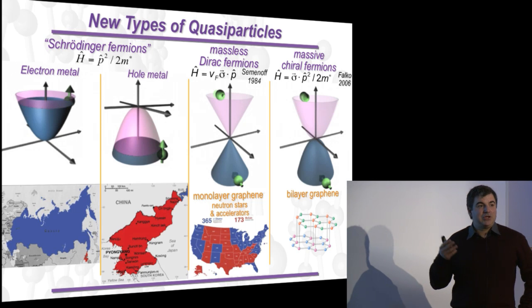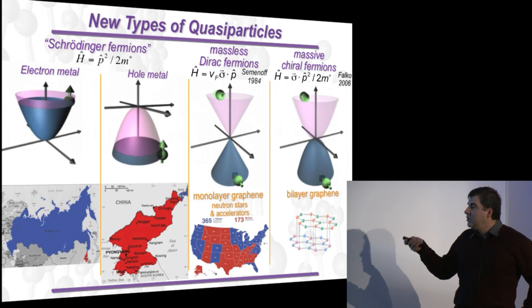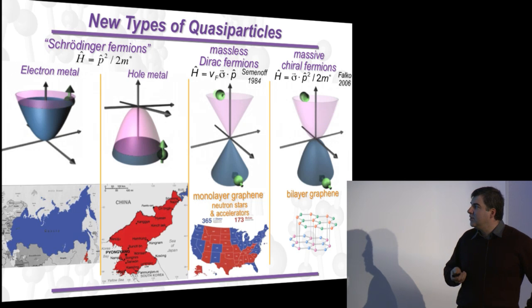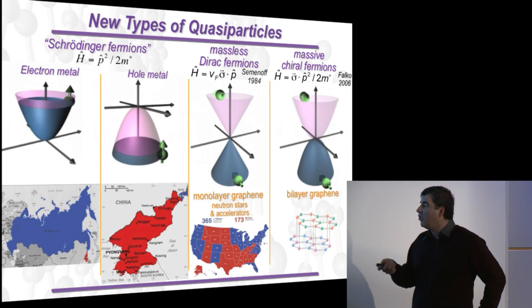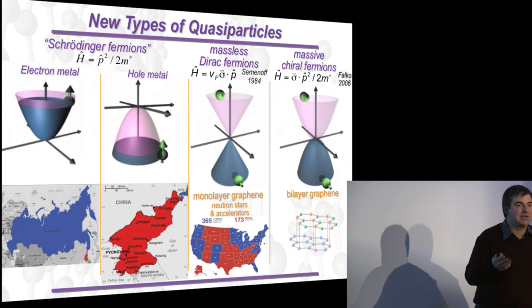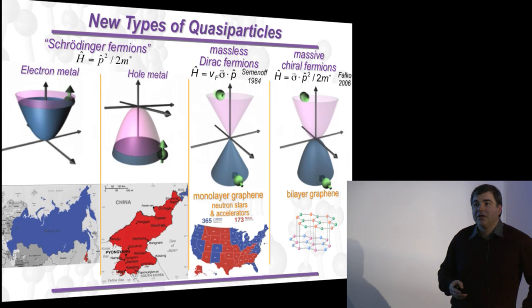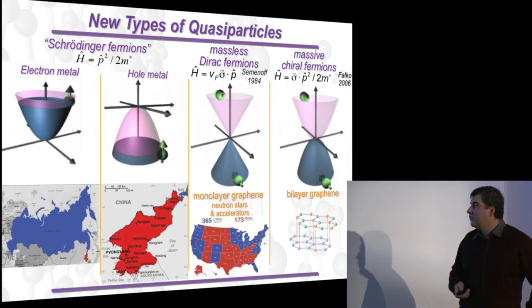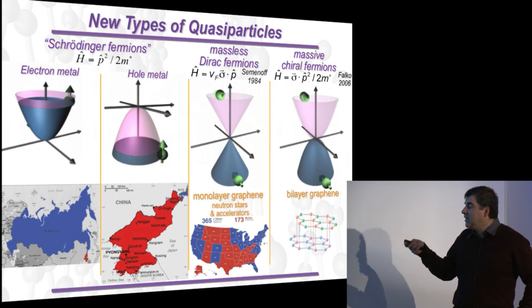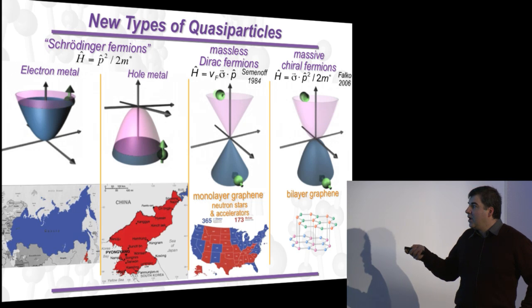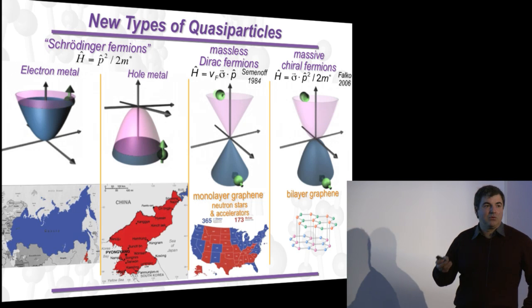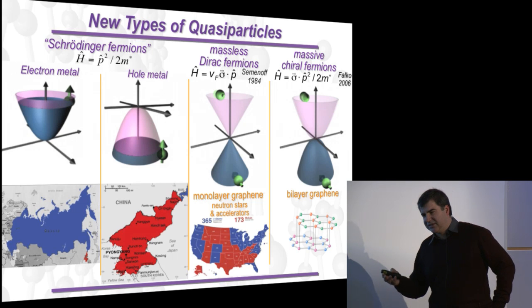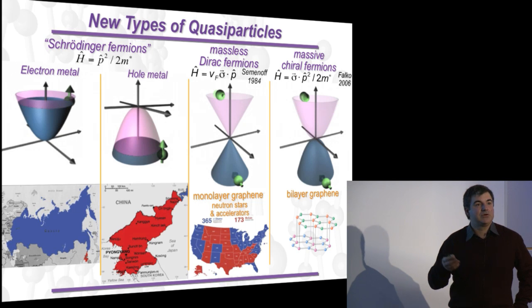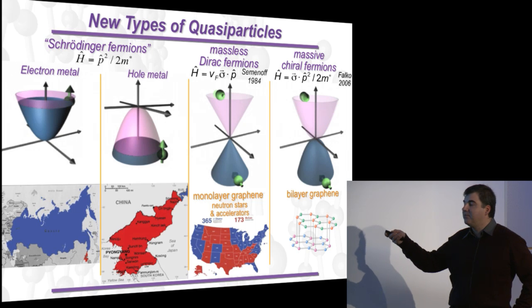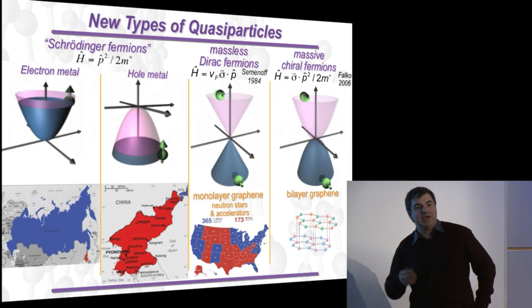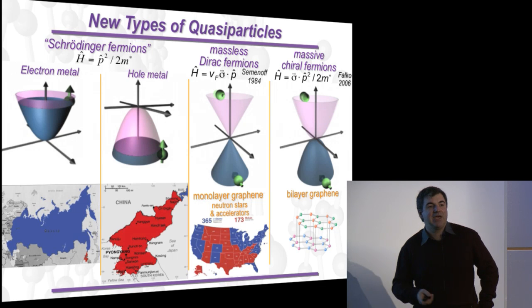In graphene, the situation is very different, because we have a linear dispersion relation. We don't have mass in the equation. There is only momentum. So we have massless particles. That's the situation which people are used to in high energy physics, for example. It means that there is a certain symmetry between your electrons and holes, the so-called chiral symmetry, or, in the language of relativistic physics, the symmetry between particles and antiparticles. They're basically described by the same equation and by the same wave function.